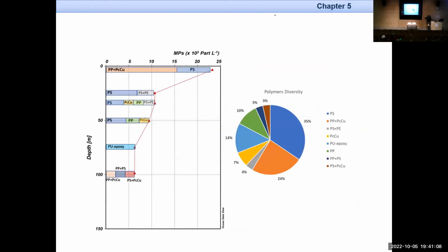So this is, again, the number of particles per liter. We found in surface water in the Antarctic around 20,000 particles per liter, and it decreases with depth. You can see the colors here are the corresponding polymers. We found polystyrene, polypropylene, polyethylene, down to 100 meters. So again, high diversity in polymers, and polystyrene, polypropylene, and polyethylene are the most common polymers found in the ocean.